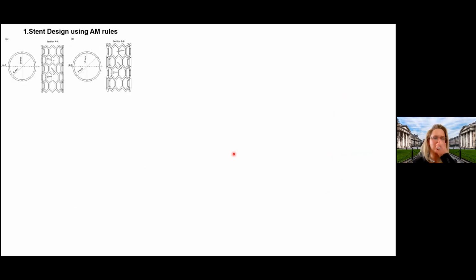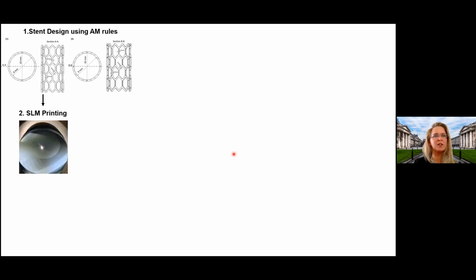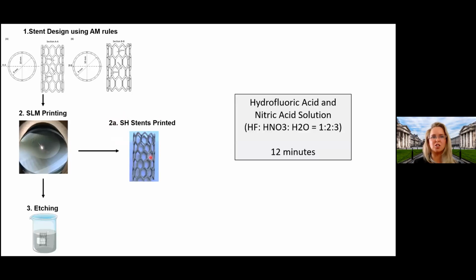So essentially what we want to do is print stent designs with additive manufacturing rules. So we do our printing. We then take those stents. This is our simple honeycomb. We have the SH, so we'll keep this acronym throughout. So SH is our simple honeycomb stents as printed. These have quite large struts. Actually, they're about 0.5 millimeter thick, as you will note from some of the previous schematics, which is very thick for a stent. Typically, stents would be around 100 microns or lower, even 50 to 100 micron strut thickness.